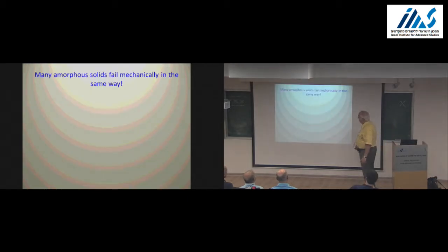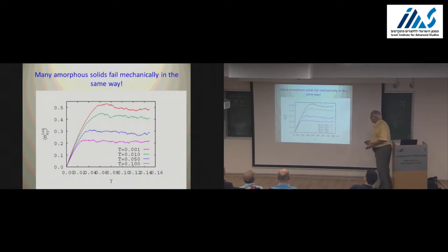The phenomenon is rather ubiquitous and universal in the sense that you look at very many different glasses or amorphous solids, and all of them have the same looking stress versus strain curve. That is to say, at small strains, this, by the way, is quasi-static, you have a sort of elastic response in the sense that the measured stress as a function of the strain increases sort of linearly. It bends, but it increases. And then there is a transition into a state we call the steady state plastic flow, where even though you're increasing the strain, the stress cannot increase.